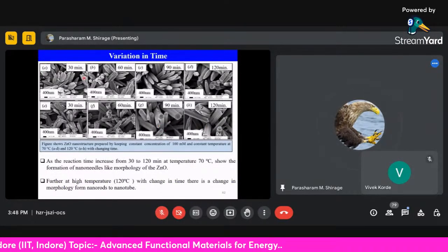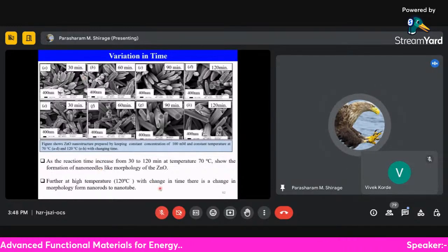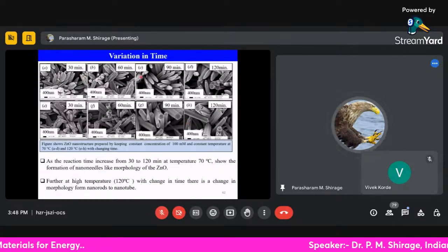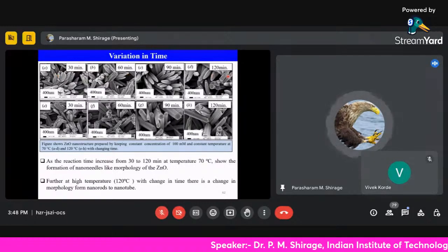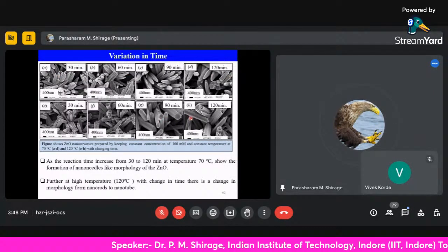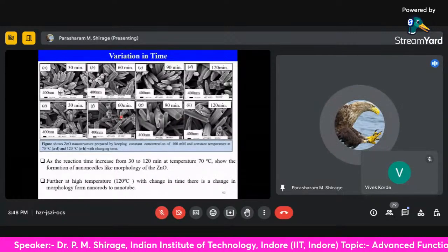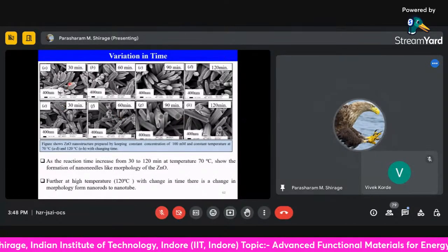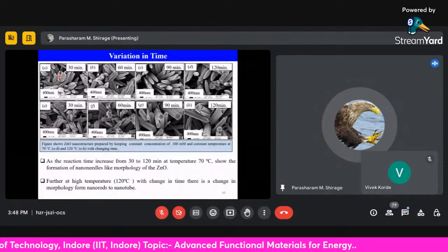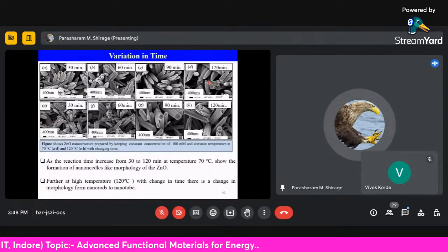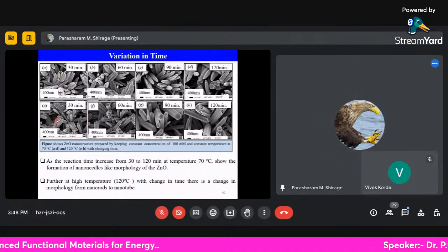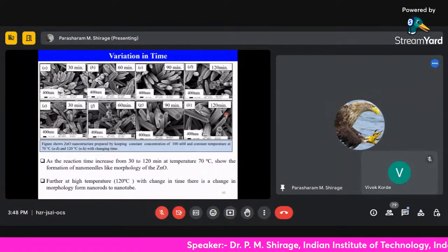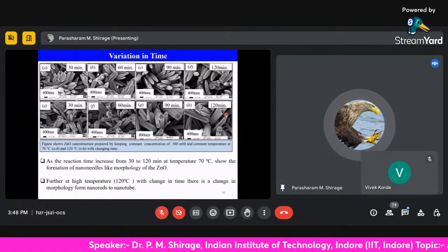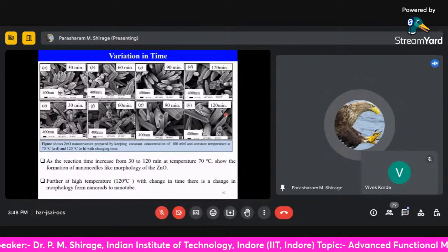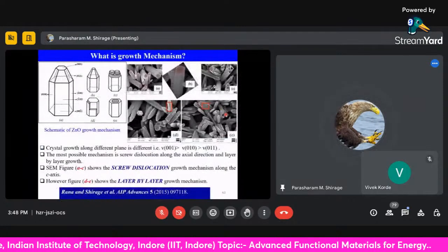This is first 30 to 120 minutes at 70 degrees centigrade, and this is prepared at 120 degrees centigrade, and concentration is the same, 100 millimolar. Okay, so you can see that this needle-like structure remains needle-like, but dimension is increasing. Rod-like structure changes from 30 minutes to tube-like structure at 120 minutes. So the duration of the preparation of the material is also very important. You have to stop the reaction at the particular time, so we can get the important thing.